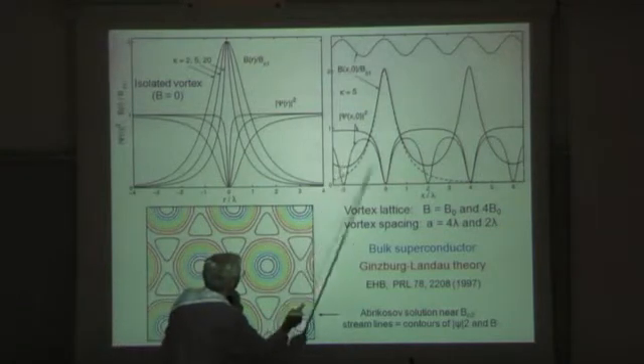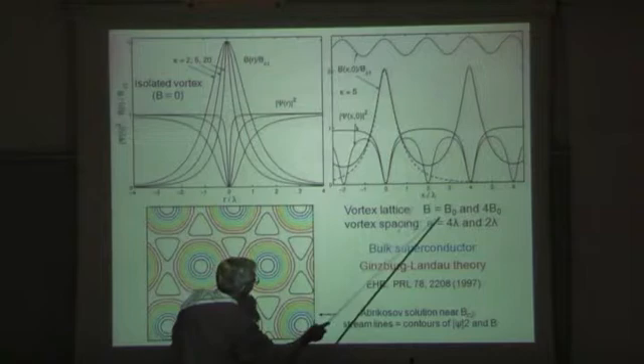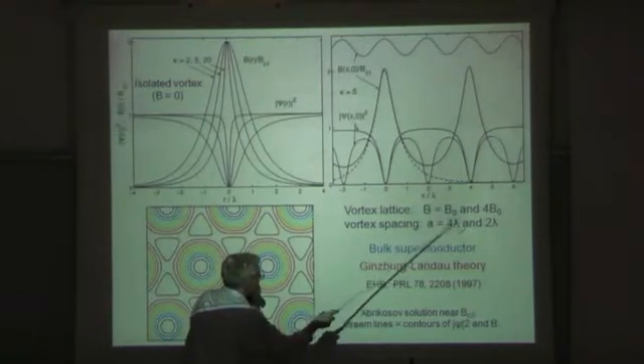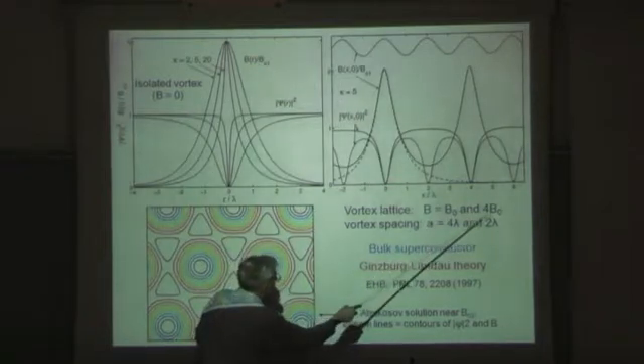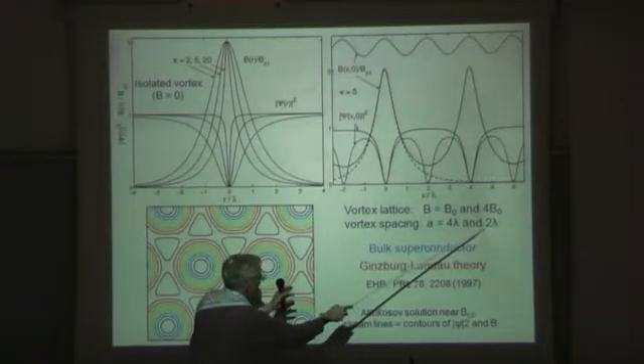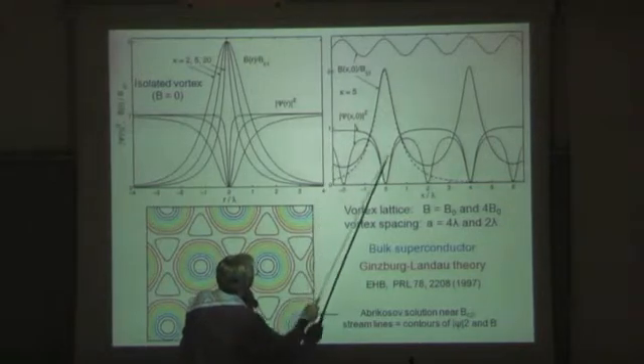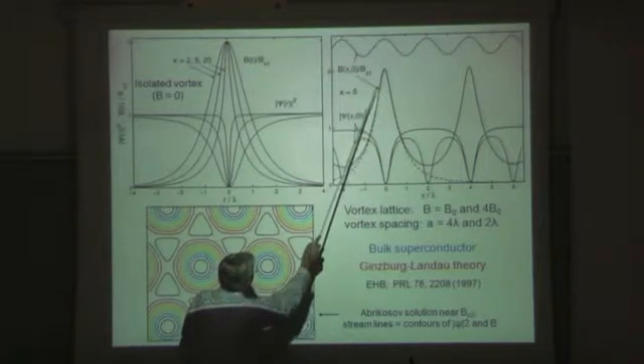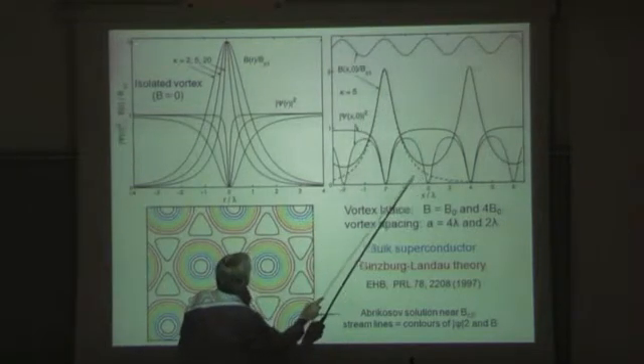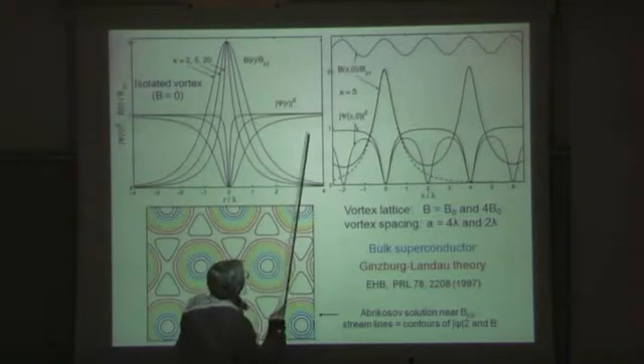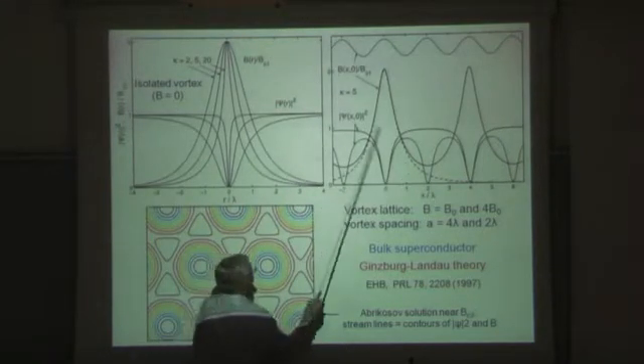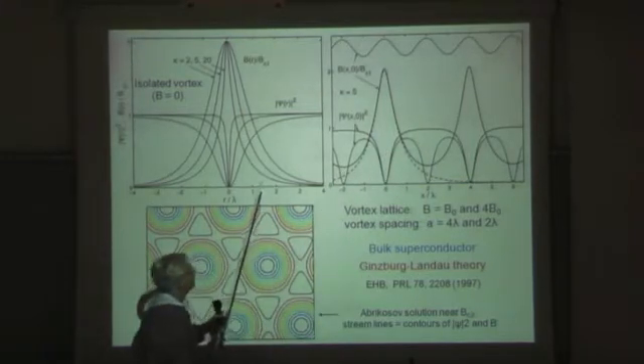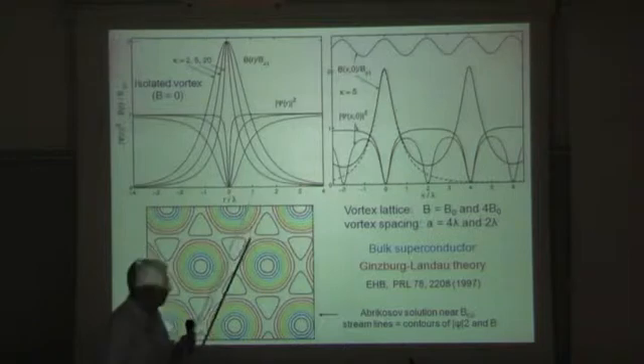Then you have a vortex lattice which is a periodic one. Here are two different densities: some field B0 induction, and then four times this induction, or just half the vortex spacing. You see the order parameter is periodic and also the magnetic field is periodic. Here at low inductions, the magnetic field is a linear superposition of single vortex fields. But at higher inductions, the magnetic field is almost constant and has only a small modulation because the vortex fields overlap.